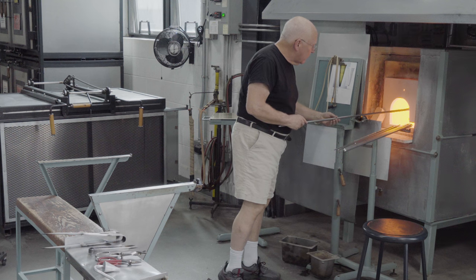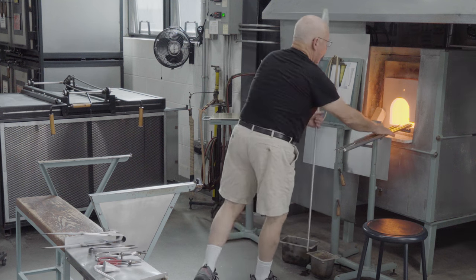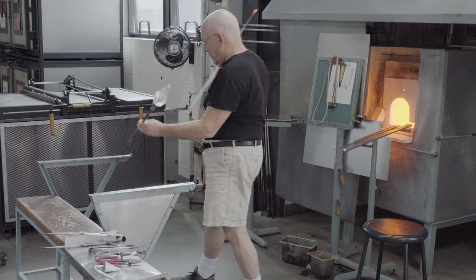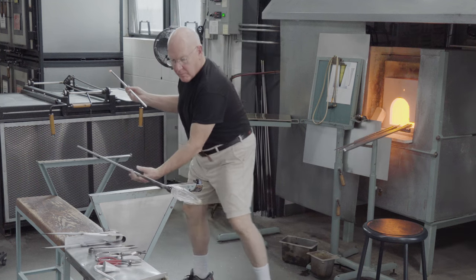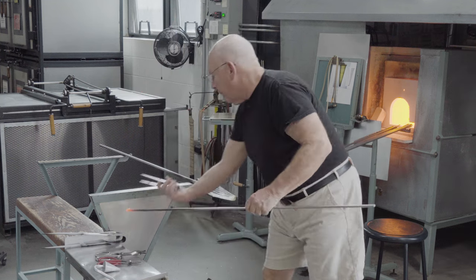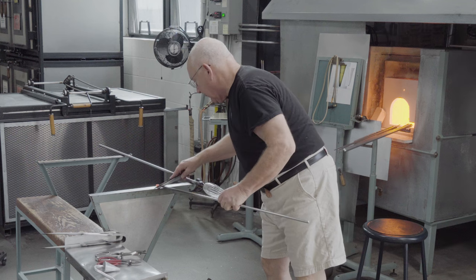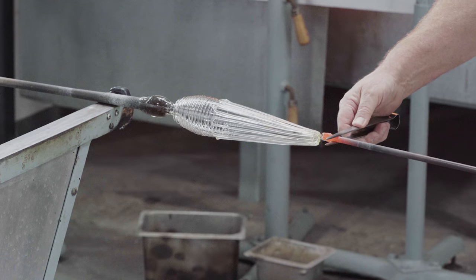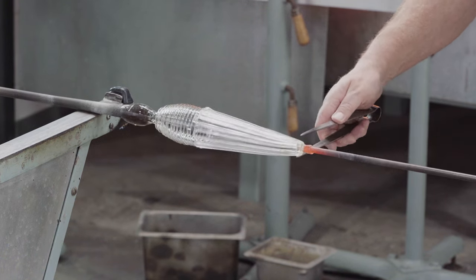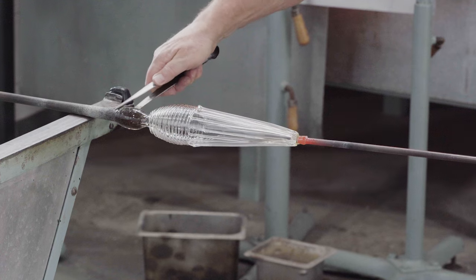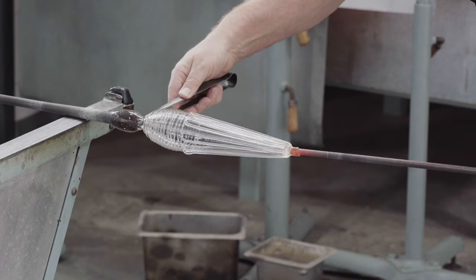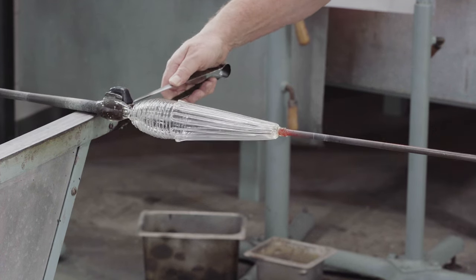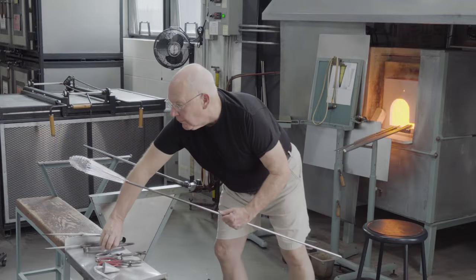After careful flashing to make sure that the spiral threads are as hot as they can be, the vessel is transferred to the punty. The punty is straightened. The tips of the pincers are squeezed in the constriction. The blowpipe is tapped, and the neck breaks.